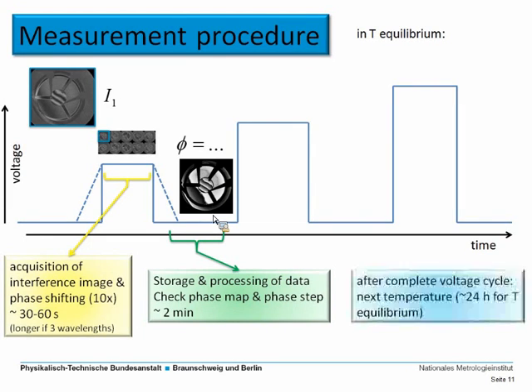And once we completed the voltage cycle, we can go to the next temperature. This takes about 24 hours to reach the next temperature equilibrium. There is still room for optimization, and we have some ideas what we can improve, but this was the measurement sequence we used for all the data I show you now.